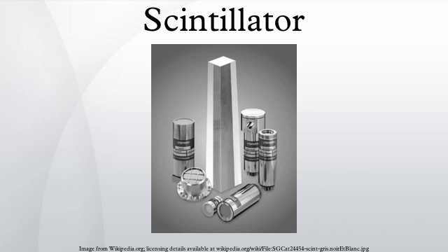List of inorganic scintillators. The following is a list of commonly used inorganic crystals. BaF2, or barium fluoride. BaF2 contains a very fast and a slow component. The fast scintillation light is emitted in the UV band and has a 0.7 nanosecond decay time, while the slow scintillation light is emitted at longer wavelengths and has a 630 nanosecond decay time. It is used for fast timing applications, as well as applications for which pulse shape discrimination is needed. The light yield of BaF2 is about 12 photons/keV.